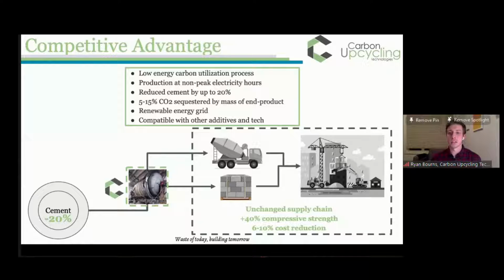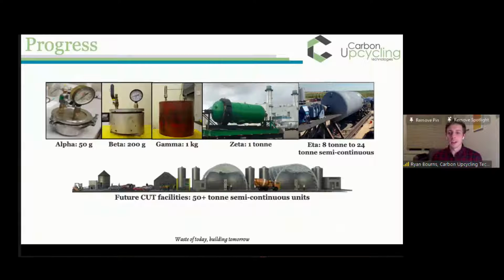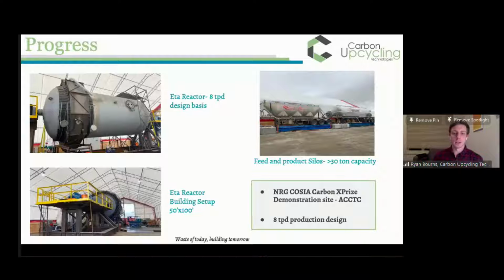And in terms of how much CO2 we're actually getting into that fly ash, it's between 5 to 15% by weight of that end product. So for every ton of fly ash that we have, there's between 50 to 150 kilograms of CO2 stored permanently in that fly ash. This is something that we've scaled up again over the last few years to the point where we went from something the size of a cookie jar to our most recent reactor, which produces about 8 tons per day. And here's, I guess, a couple more pictures to describe this. And this is something that we have at our demonstration facility in Calgary. And as I mentioned, we're producing about 8 tons of product per day at this point.